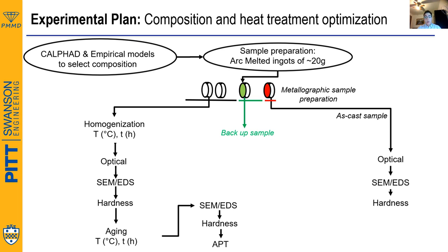The methodology and the experimental plan that we carry out to achieve this goal is laid out here for you. By following the CALPHAD approach and empirical models, we develop a high-throughput ICME framework that allows to explore these steel's multi-component system and screen compositions that would maximize the volume fraction of the desired L21 phase while minimizing the other detrimental phases common in the iron silicon titanium system, such as the Fe2Ti C14 Laves phase.